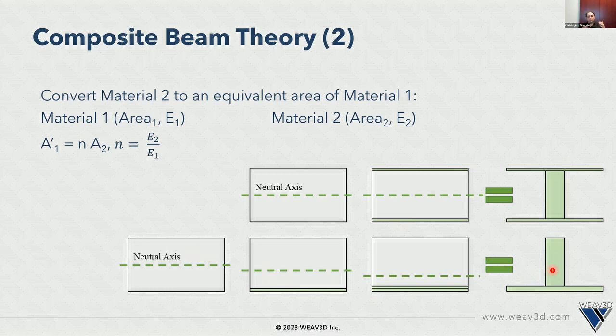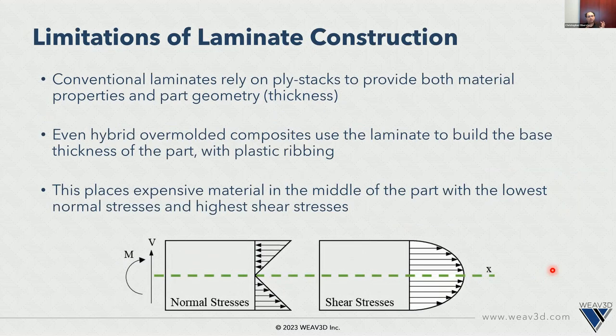So you're basically getting a sort of virtual structural shape by having these two different materials in the structure. This is also why in a lot of laminate designs, we use core materials. They're basically doing the same thing by creating these sandwiches. One of the challenges when we're talking about laminate construction, particularly things like organosheet, which the back half of this presentation will focus on, is that the laminate is basically building both your thickness of the part and the material properties of the part.